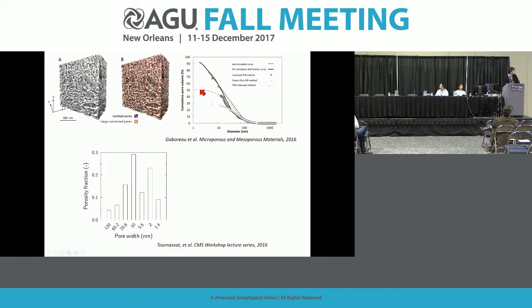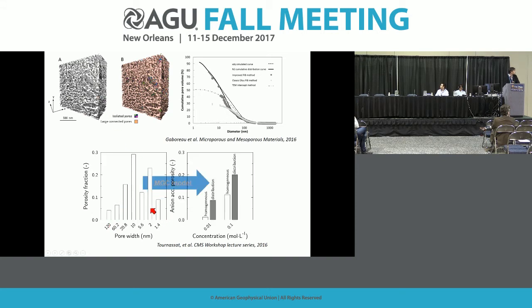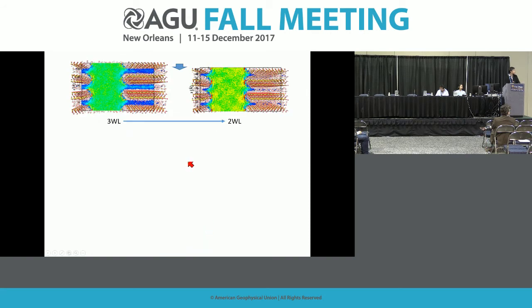Now, if we take this information about the porosity fraction as a function of pore width, you can obtain such a histogram for this clay sample, and you can apply the Poisson-Boltzmann equation and compare the effect of a distribution of pore sizes to a homogeneous pore size distribution. What you can see is that, for example, for the anion accessible porosity, you can have a huge effect as a function of ionic strength. Usually, if you have a distribution of pore sizes, you have more access for the anions than if you consider a homogeneous system. We also have some information from molecular dynamics: for 3 water layers, you can have access of chloride, for example, in the interior pores, meaning 1 nanometer pores.